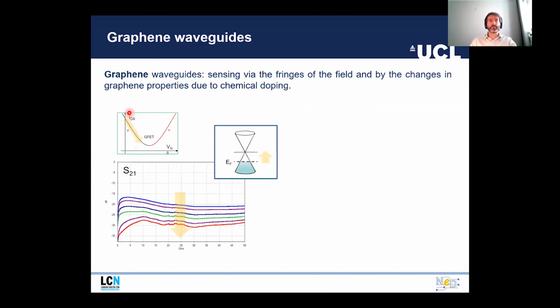So if we look, for example, at a coplanar waveguide where we can tune the position of the Fermi energy by using a suitable gate, we can see that the transmission of the waveguide, summarized by the S21 parameter, goes down as the Fermi energy goes closer to the charge neutrality point, which means we have this kind of loss, a reduction of transmittance depending on the gate.